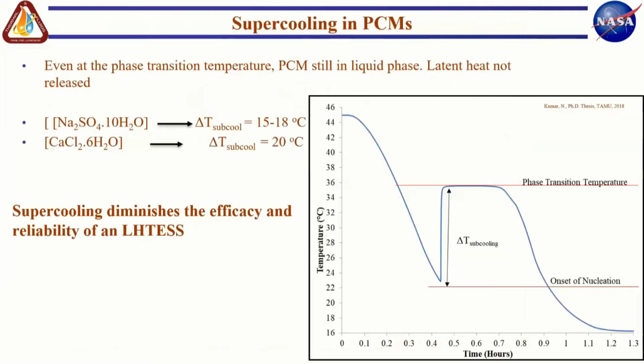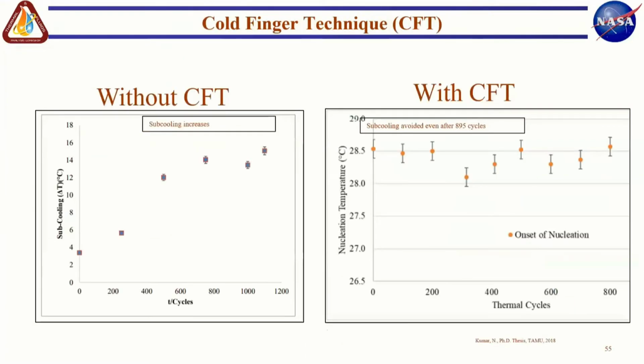But the enigma there is you don't want to melt the PCM 100%, because if you melt it, now it requires a substantial amount of subcooling for onset of nucleation to work, and you have wasted precious hours at night just waiting for the PCM to solidify, or to initiate the solidification. So the way to get around it is to use what is known as the cold finger technique, which is you keep a part of the PCM unmelted.